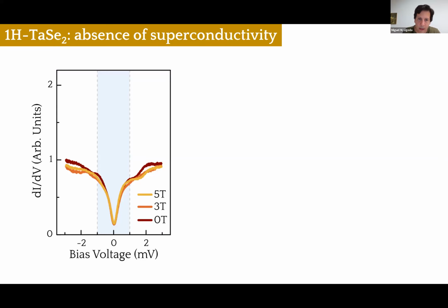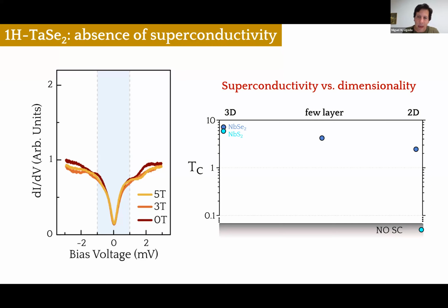This is interesting because tantalum diselenide turns out not to be a superconductor at 300 millikelvin, and the behavior of superconductivity in this type of materials, in this type of TMDs, versus dimensionality shows a quite distinct character. For example, the niobium family of TMD materials show a decrease in the critical temperature, or I mean, superconductivity is weakened with the number of layers. In the case of niobium disulfide, it actually disappears. Superconductivity is not sustained in the single layer form. In the case of niobium diselenide, it's a bit weakened, but it survives between 2 and 3 Kelvin.